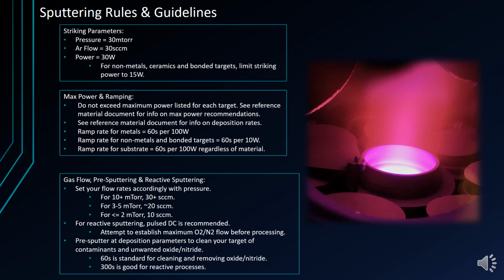When pre-sputtering, it's recommended that you do about 60 seconds for cleaning off contaminants and unwanted oxide or nitride surfaces on the target that may be left over from a previous process. If you are performing a reactive process, then 300 seconds is recommended for a pre-sputter. This is due to the reactions taking place at the target surface. You will want to let that process reach equilibrium before opening the shutter.